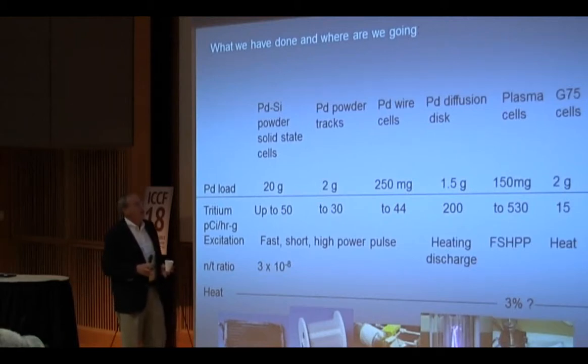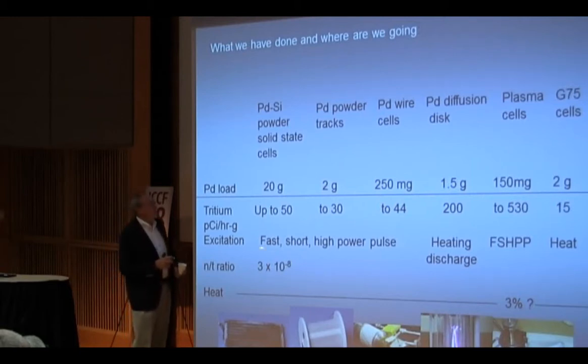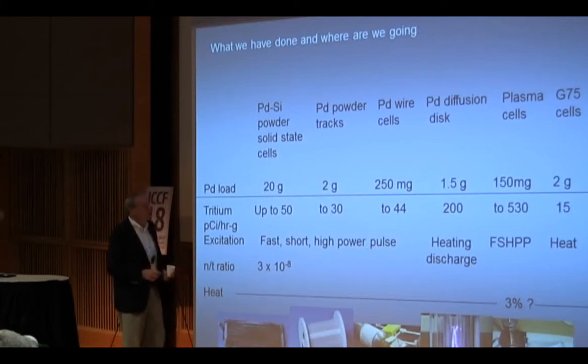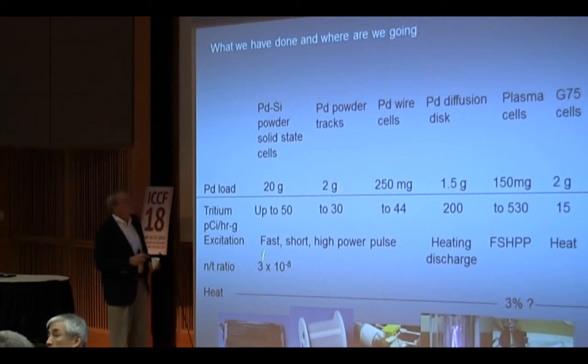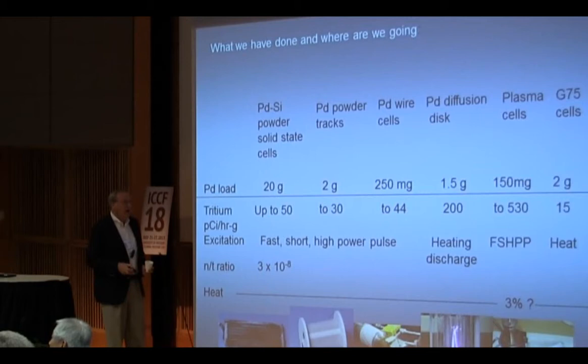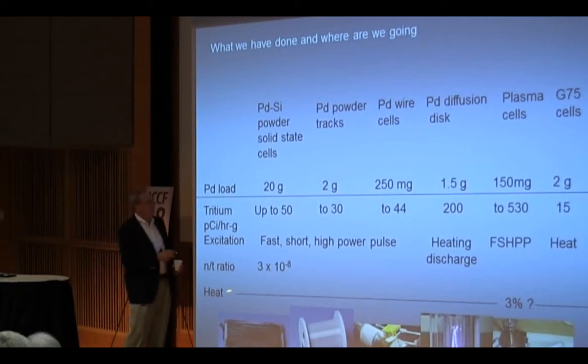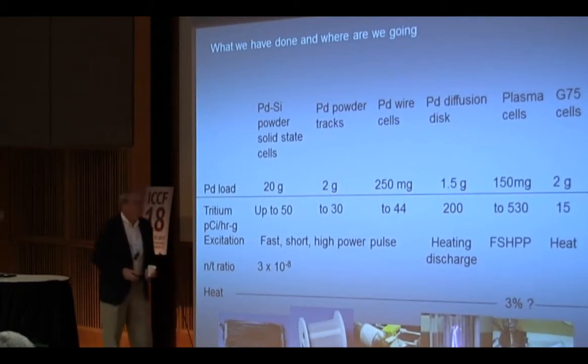That's why we're screening the materials in a plasma system. And these are all fast, short, high-powered pulses. This was a heating and a discharge on this diffusion cell. And then this was just fast. This was just heating. Okay. So the neutron to tritium ratio we measured in these cells to be 3 × 10⁻⁸, and we didn't know that. We found out later that this was the low ratio. I mean, we were sitting on this result because we didn't believe it.